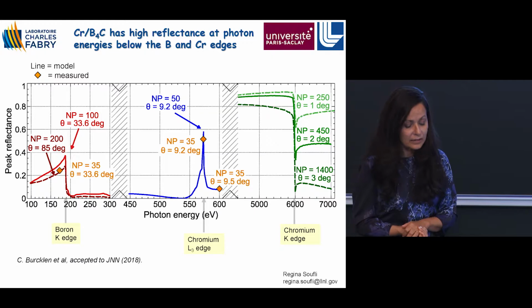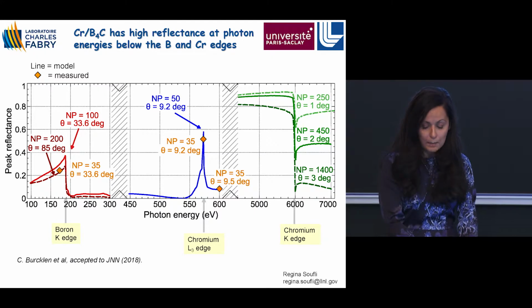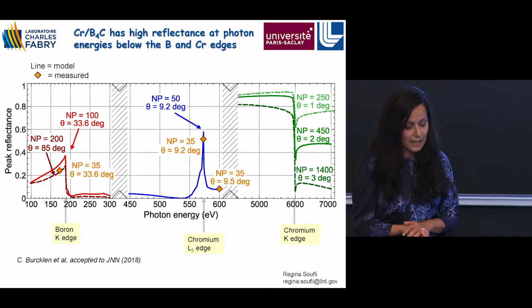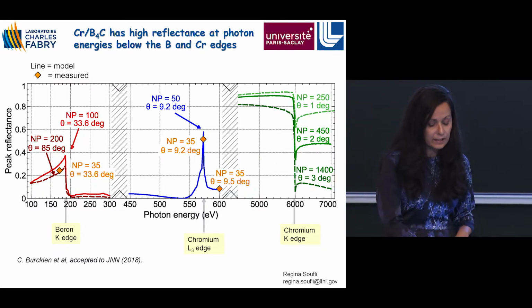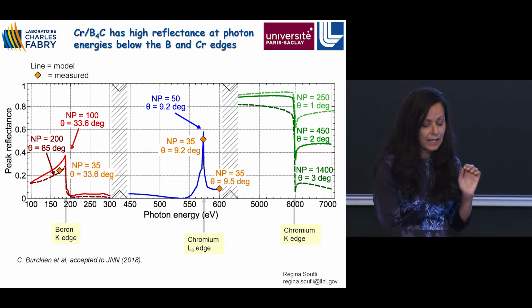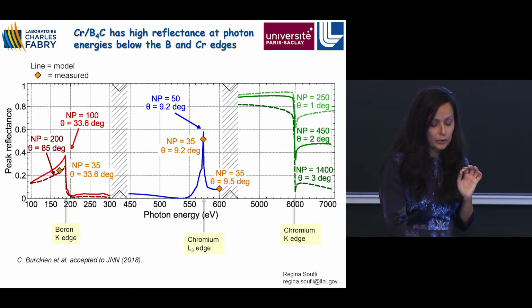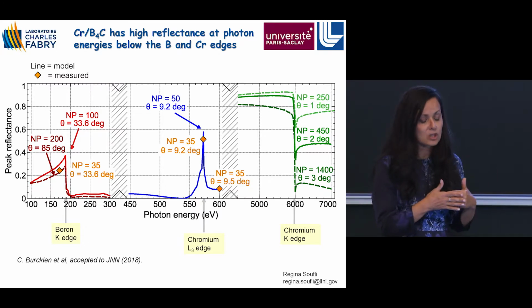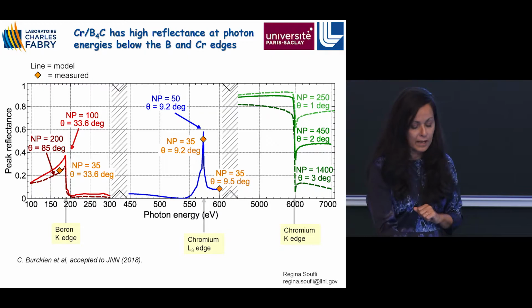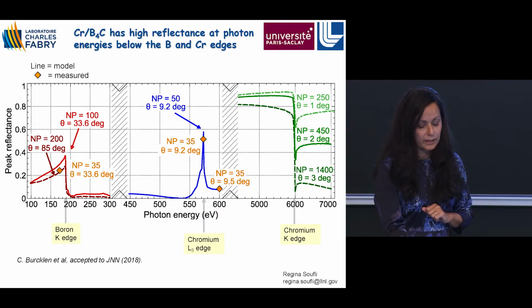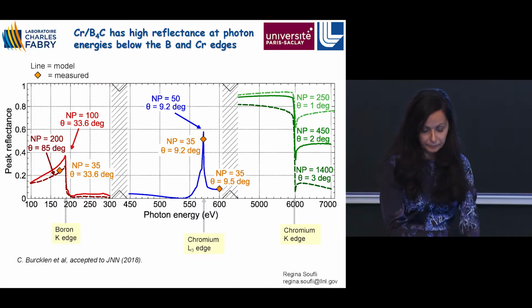So we decided to investigate this phenomena using this chromium boron carbide multilayer coating. This is a coating that has been pioneered by the group at LCF due to its potential for high reflectivity in the regions of the boron K and chromium L and K edges. As I was mentioning again, below these edges is where boron or chromium have low absorption, and this is the chance to get high reflectivity. So we very often operate at these photon energy regions. So I'm showing here peak reflectance versus photon energy at specific angles of incidence, and NP is the number of periods in the multilayer. So again, you can see the high potential of this coating and the high reflectivity that you can achieve.